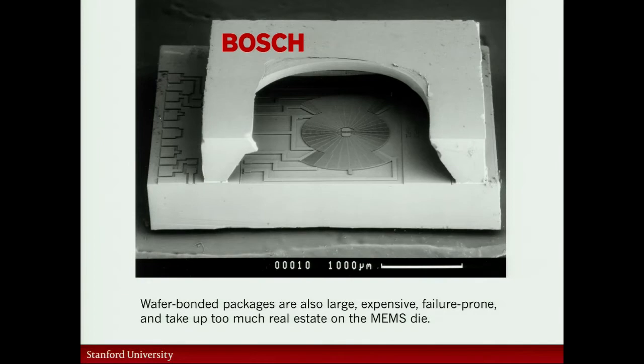So we still build a lot of MEMS devices using conventional wafer bonding techniques. This is a 15-year-old picture from Bosch that I got from Marcus Lutz. There's been some improvements. There's still a lot of similarity to what's shown here. You have a tiny micromechanical element enclosed in a fairly large chamber, covered with a bonded wafer that's sealed with a glass frit around the perimeter.